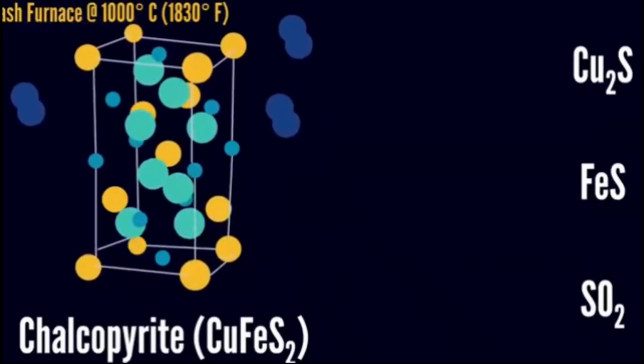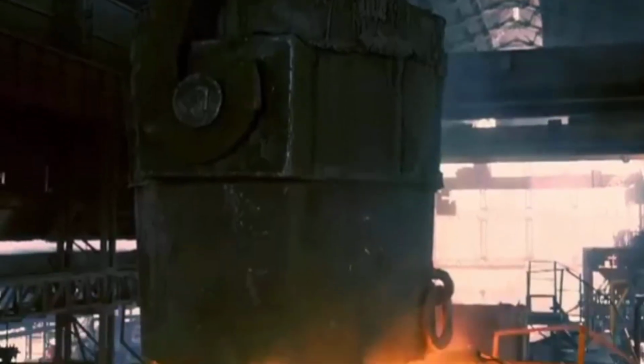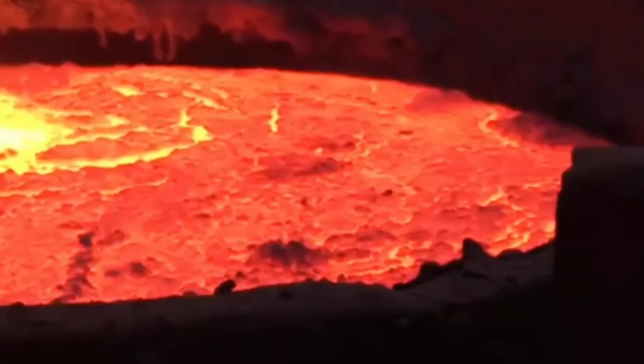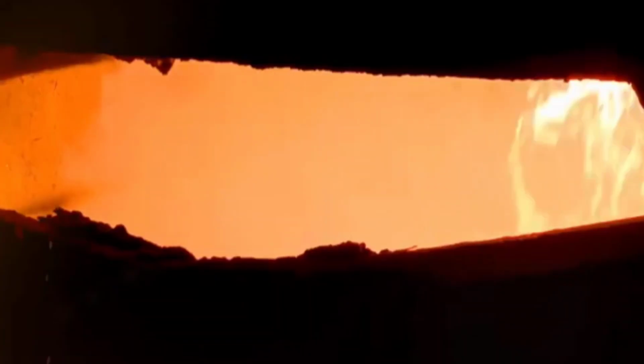Elements like iron react with the silica to form a lighter, molten slag that floats to the surface, much like foam on a boiling pot of soup, while the denser molten copper settles at the bottom, dark and heavy like thick syrup. The result is what's known as blister copper, named for its rough, blistered surface as it solidifies.